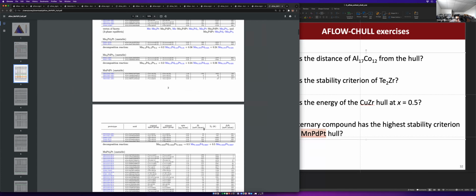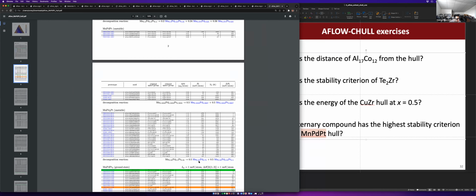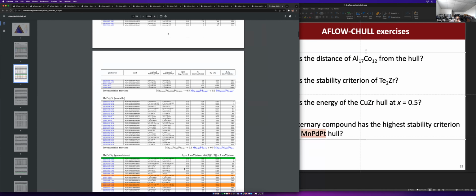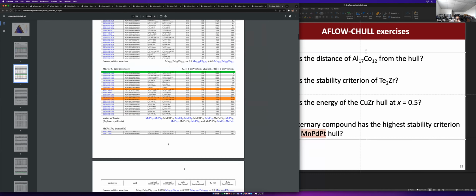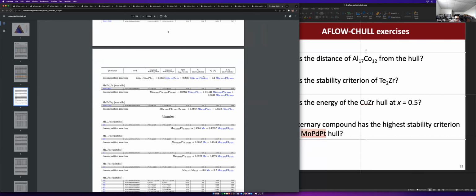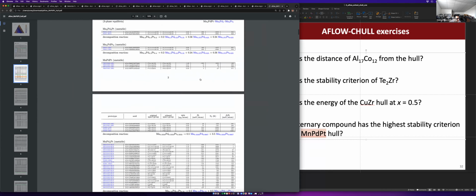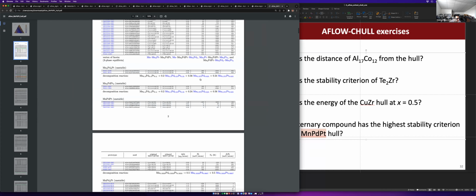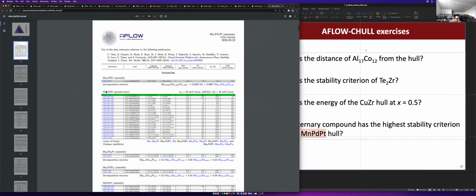We should have one more. We have one that is 1 meV per atom, and that's it for the ternaries. So the one that has the highest stability criterion is this MnPdPt, and this one actually turns out to be the composition of that magnetic system that I talked about earlier. You can see that it's higher than 30 meV per atom, which is why we were able to find it. Okay, any questions on those exercises?